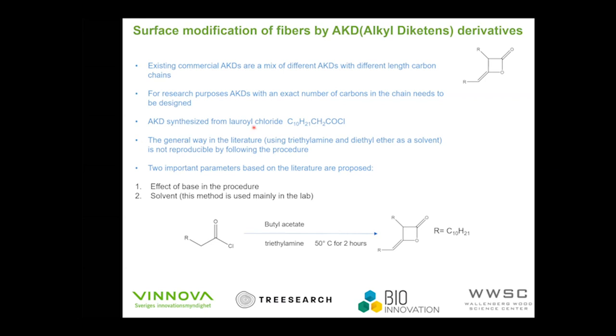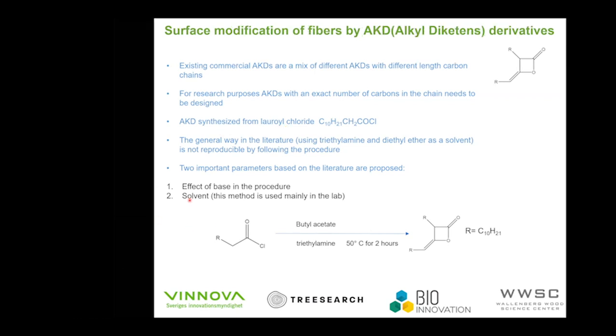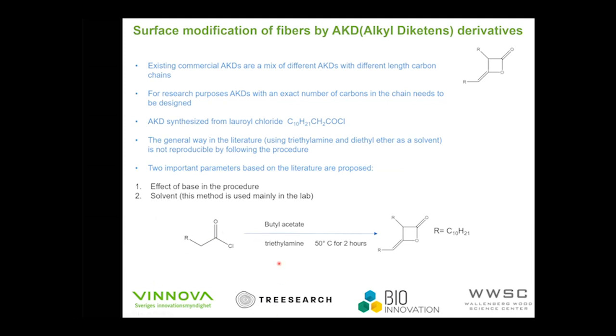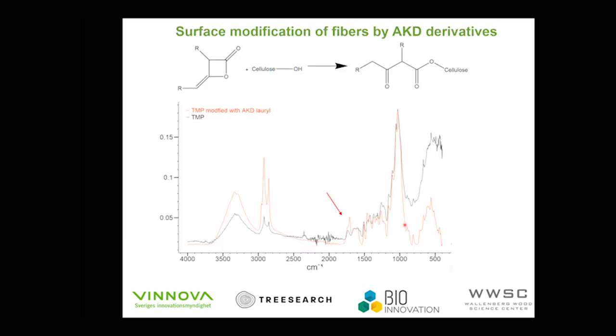The general method in the literature, using triethylamine and diethyl ether as a solvent, was not really reproducible. So we played around with the reaction a bit. We tried adding a base or changing the solvent. Actually, we mostly changed the solvent, to butyl acetate. Briefly, the reaction happens in 2 hours at 50 degrees, and we have a reproducible product.